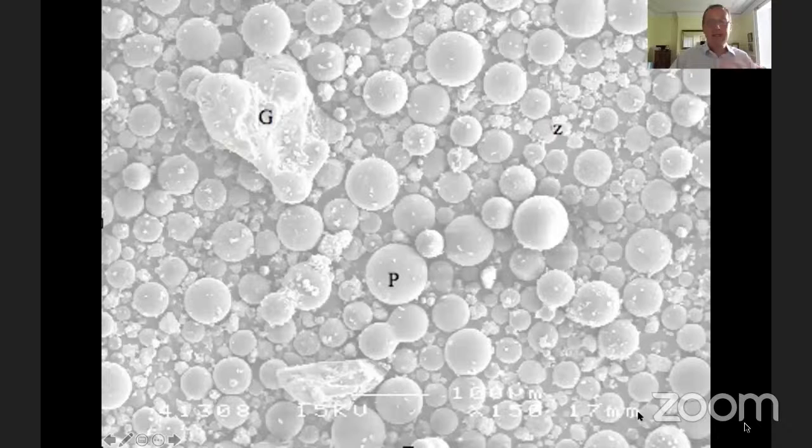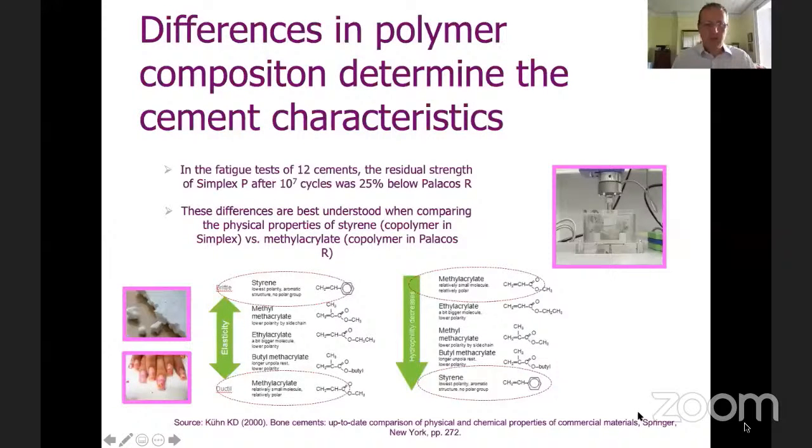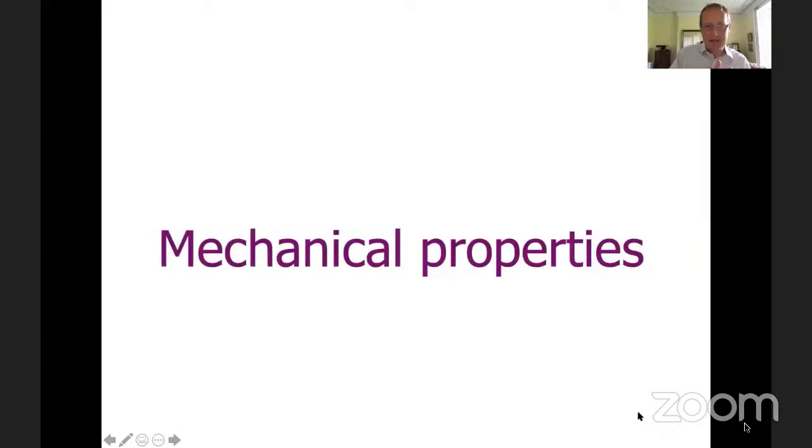It's fascinating on a chemical level, and it's those differing constituents that vary the behavior of this useful biomaterial. And so one thing that's interesting is the modulus of elasticity, the stiffness of it. And as you go more hydrophilic, then you become more flexible. And so it's the methyl methacrylate copolymers that make it more hydrophilic and increase its elasticity, as we'll see in a minute. So those chemical aspects are key to then denoting the mechanical properties. Remember, all of these things, as usual, come about largely by chance, but where then people recognize the differences and then can extrapolate and utilize them is where these things become so useful in medical practice.